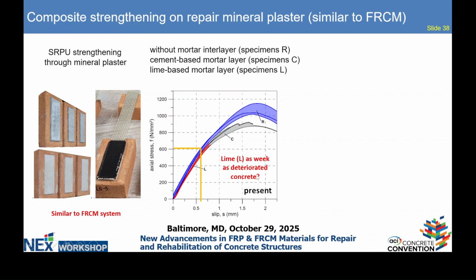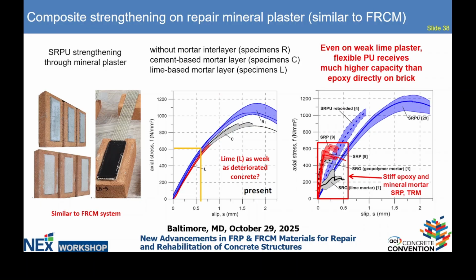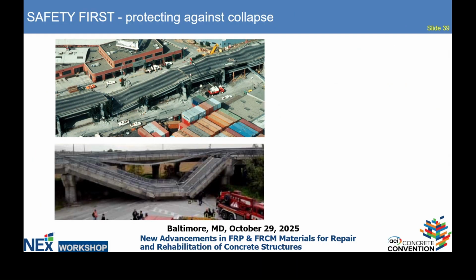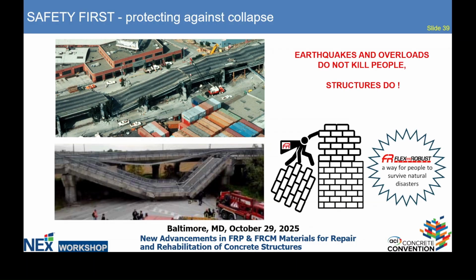So, can we assume that lime mortar is the deteriorated concrete? Let me assume. In this case, when we compare with some literature, this is the same area. So you can see the effectiveness of SRPU and also some FRCM systems compared with this polyurethane system. It is much more effective, especially much more ductile. So when we go to structures and sudden falling down, safety should come first, yeah? So we should protect the structure against that. And flexible polyurethane joints and adhesives were developed by FlexAndRobust System to keep the structure in position.